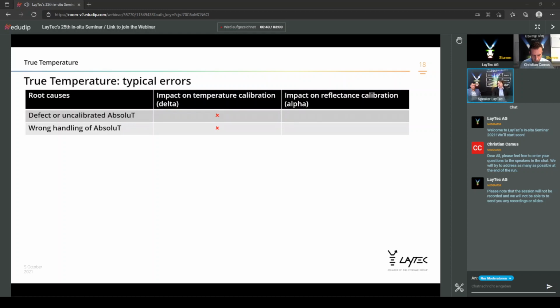So even though you would hold the absolute T right into the center axis of the viewport aperture, it still might lead to a wrong result in delta calibration if you don't hold the face plate or the face surface of the top cover of the absolute T flush to the opening or to the ceiling or to the reactor lid. This can lead to the emission being reflected or clipped by a sidewall or an edge of the optical channel of the viewport of the aperture, and then again lead to a wrong delta calibration because the amount of light reaching the detector for that particular temperature on 950 nanometers or 405 nanometers in terms of the Pyro 400 does not correspond to the expected reference value.